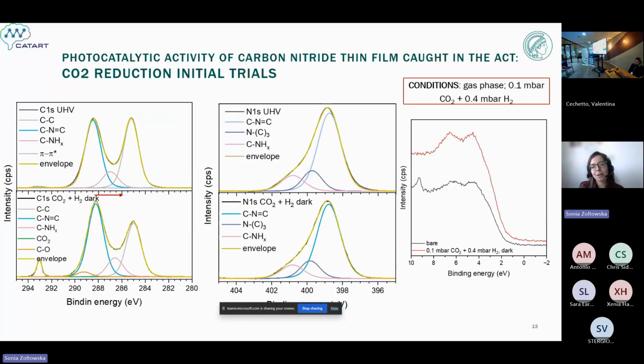And our very preliminary study showed us that we are going in a good direction, because if we look at those XPS spectra here on the top, measured of course in ultra high vacuum conditions, and then on the bottom measured when the mixture of CO2 and hydrogen was flowed, we see again the signature of the adsorption. If you take a look at the carbon level spectrum, we can see the shift of the features towards lower binding energies, and also formation of two new species, adsorbed CO2 and also a CO feature.